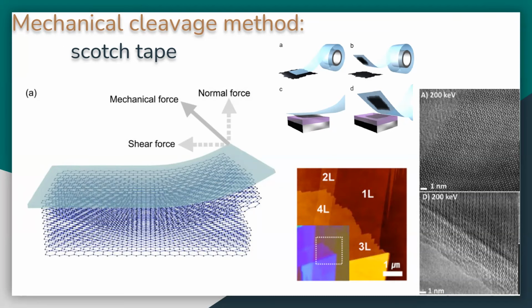However, to the right of the colored image, an electron microscope will actually show the molecular order of the exfoliated layer. The brighter spots belong to the heaviest atom, which is the chromium, and phosphorus and sulfur cannot be explicitly identified since they are so close in mass, but the earlier slide on composition ratio does show they were ordered correctly throughout the sample.